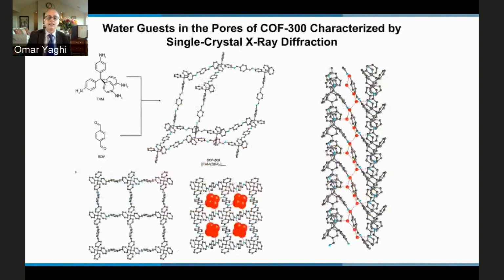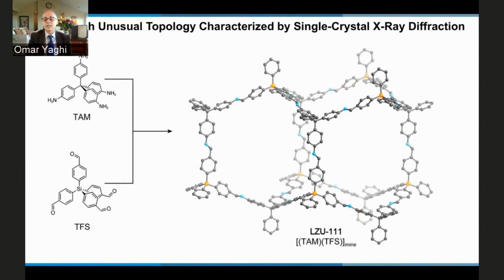So did we get the structures right? For the most part, we got them right from powder diffraction, but there are certain things we didn't get right. For example, we couldn't decipher the water structure within this COF. So you see water chains that we could not fully appreciate from the powder diffraction. And so, yes, there's a lot of value in getting single crystal structures, and that's why it's the holy grail in materials characterization. You can also make structures that you couldn't predict. For example, when you link tetrahedra together, usually you make cubic diamond topology. But in this case, you make the hexagonal diamond structure, which without a single crystal structure, we couldn't have characterized.